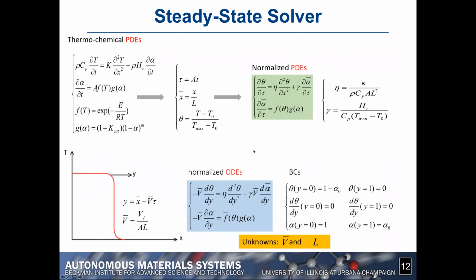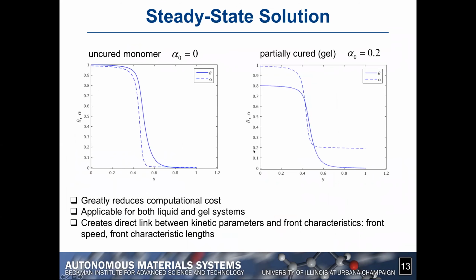And so here's a typical result that we get that looks very similar to the movie that we just saw earlier. On the left side, you have the description of the thermal front, the solid curve, and the dash curve is the degree of cure, for the case of alpha 0 equals 0, meaning there's no initial degree of cure. On the right-hand side, you have a similar kind of plot, but for the case of alpha 0 equals 0.2. So we're talking about a partially cured, or a gel, system.